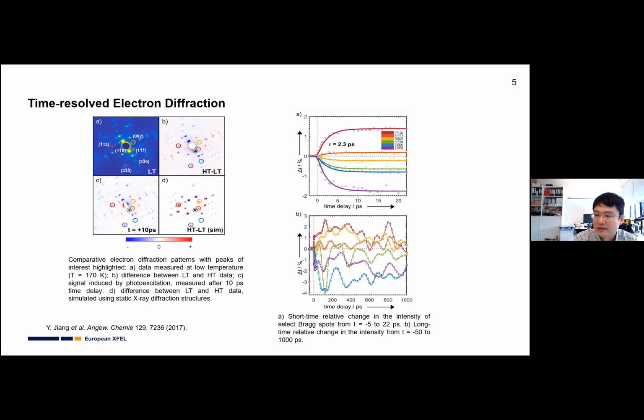The last one is the difference between low T and high T data. We use it to simulate what signal we are supposed to see. We can see B, C, D all match very well. That means we did pump the sample to the high spin state, and the structure is very similar to the thermal-induced high spin structure.